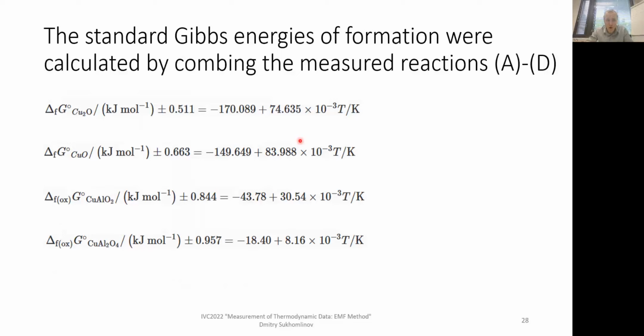And here are Gibbs energies of formation for Cu2O, for CuO, calculated from those 4 galvanic cells measured. But what I must say is that the last 2 equations are not classical standard Gibbs energies of formation. They are Gibbs energies of formation from component oxides, not from elements.